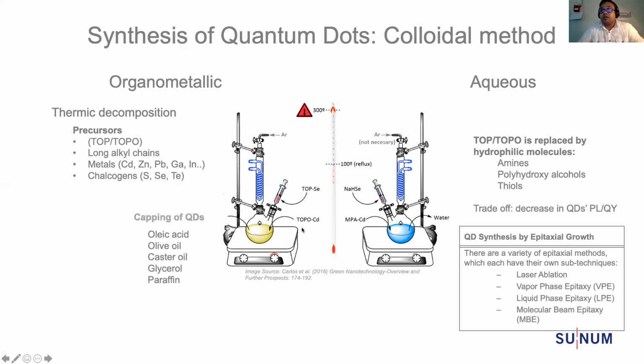All that you need to maintain in the reaction is the flow of argon, because it is anoxic. You don't want oxygen to enter into it. If it enters, there will be no crystallization taking place. As soon as the precursor is injected into the reaction, within 2 seconds, you start to get the crystals. We need 2-3 people to handle this reaction at a time, because if you delay, you will get a different size nanocrystal. This is one of the problems that we faced while synthesizing in our lab. I'll talk about that in a minute. How to control the size is the main challenge.